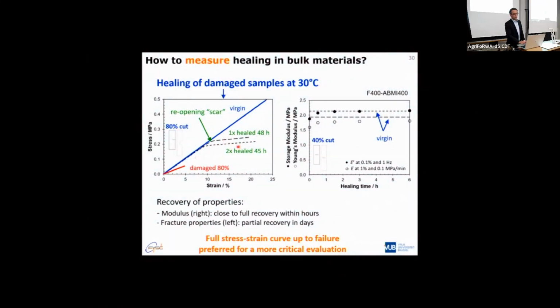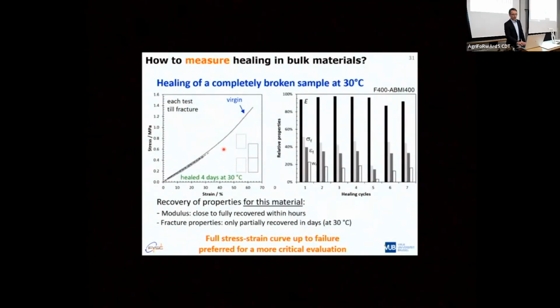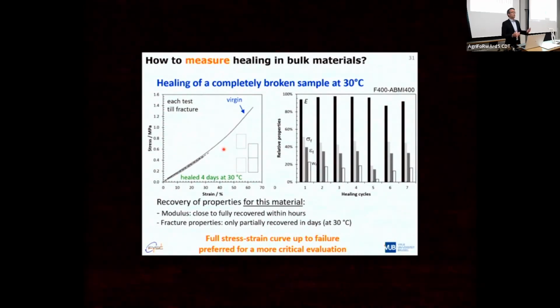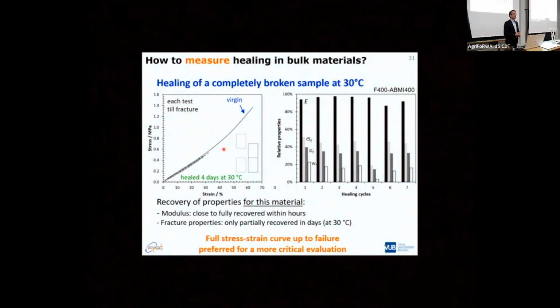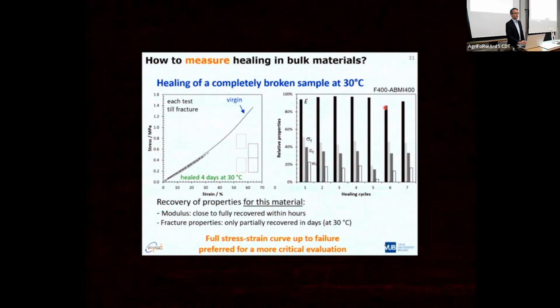So certainly measuring stress-strain curves up to failure gives you much more insight in the extent to which the material really healed. And of course, all these properties will give you a different measure of healing efficiency. You could use the modulus and get very nice values. You could use stresses or strains. They are already much lower. And if you use toughness, then you see that we healed, in this case, something like 20% instead of 90 or more percent that we have for the modulus.